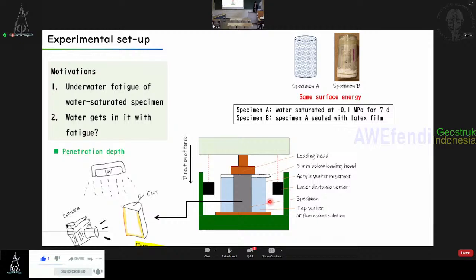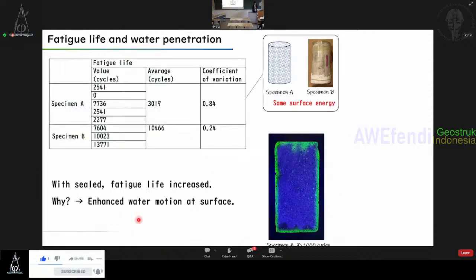The second test was penetration depth. To trace the water penetration, we used a fluorescent solution, fluorescein sodium solution. After a certain number of fatigue cycles, the specimen was cut in half and exposed to ultraviolet light. The yellow color is due to UV light, and we measured the depth of the yellow colored area. So we had 2 tests. One is fatigue life, how long it can be stable under water. The second test is the water penetration depth.